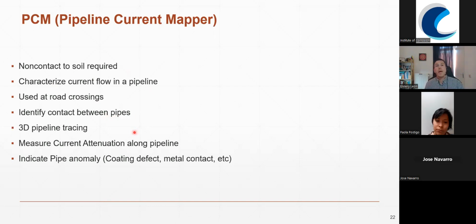We can do 3D pipeline tracing in the sense that this one allows us to get information about how deep is the pipeline. This is quite useful in pipeline corridors where we might have 2 or 3 pipelines crossing each other, and maybe we have a 2D plot and we don't know which one is on top of the other. With the PCM, we can have information about how deep each one of the pipelines are. We can measure the current attenuation along the pipeline, and we can indicate pipe anomalies like coating defects or metal contact with other structures, etc.